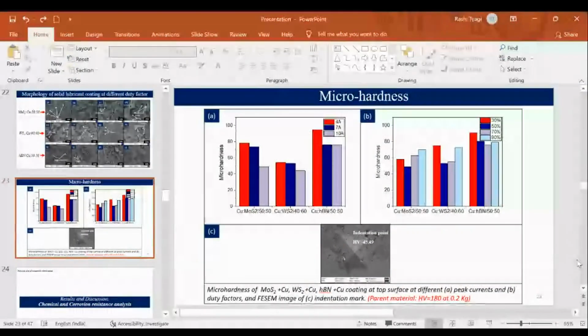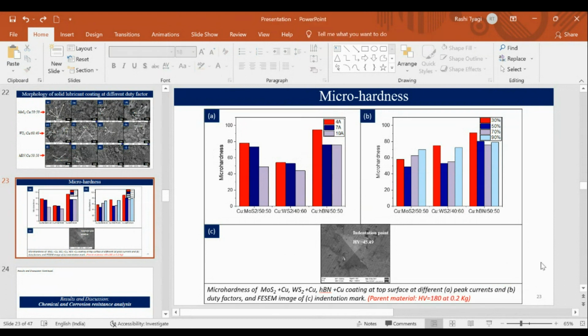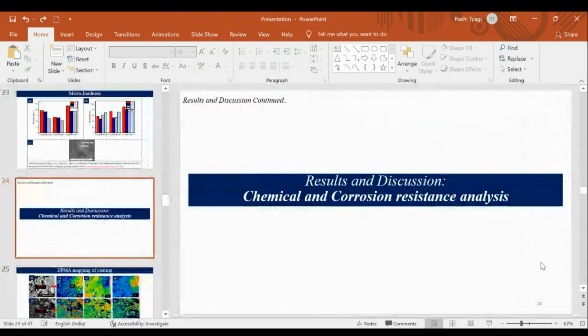So this is the microhardness. Basically, we are using soft powder, as I have already told you, so due to this soft powder the hardness will be lower in this process. This is measured by indentation marks. This is the Vickers hardness test that we have done, in which all the hardness values were very low. Parent material hardness was 180 at 0.2 kg. All these coatings showed low hardness, as you can see, 60, 80, 20, 40 as compared to the parent material. Why? Because we are using the solid lubricant.